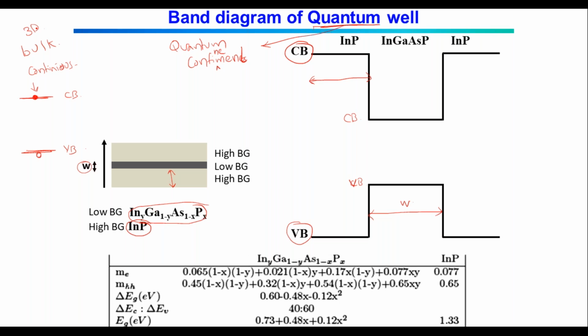But once you have a quantum well, if I put an electron inside this quantum well, so here I have an electron there, the motion of the electron is restricted along this direction, because this electron cannot go to the other side, because indium phosphide has a higher potential. It cannot go to the left-hand side because again indium phosphide has a higher potential. That means the electron is confined to stay only inside this semiconductor material, that means indium gallium arsenide phosphide. In other words, the electrons are confined.